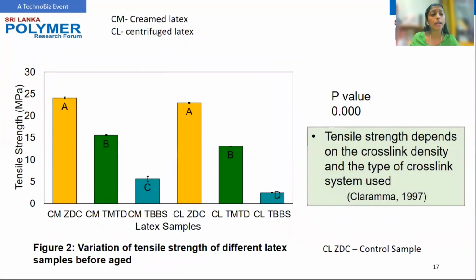The next point I would like to discuss is the tensile properties. Tensile strength depends on the crosslink density and the type of crosslink system used, as discussed by Claramma in 1997. Take a look at figure 2. As mentioned earlier, the cream latex ZDC system could be considered the best of the candidate systems if tensile strength is considered. When the tensile strength of the TBBS systems is considered, they have recorded low tensile strength values with a significant difference.